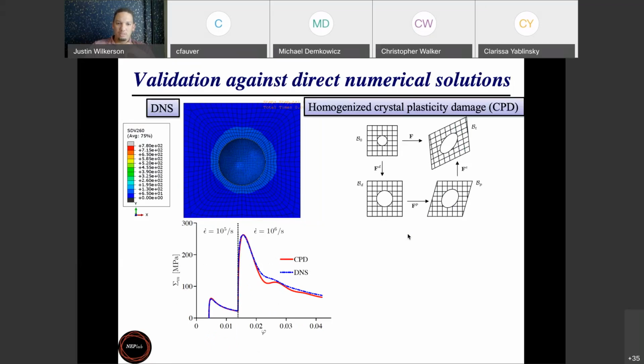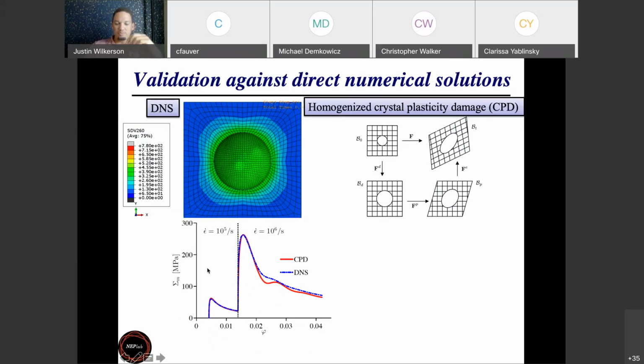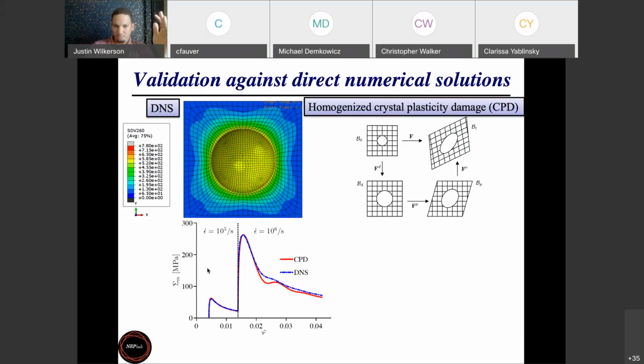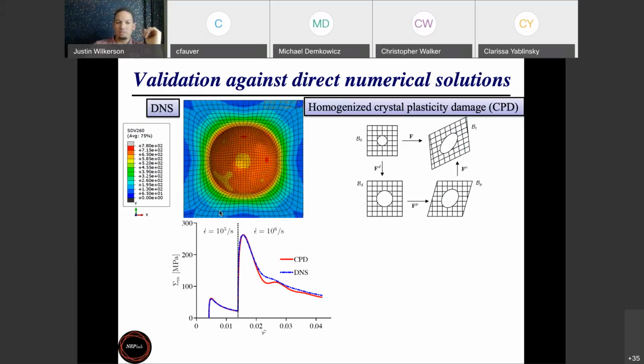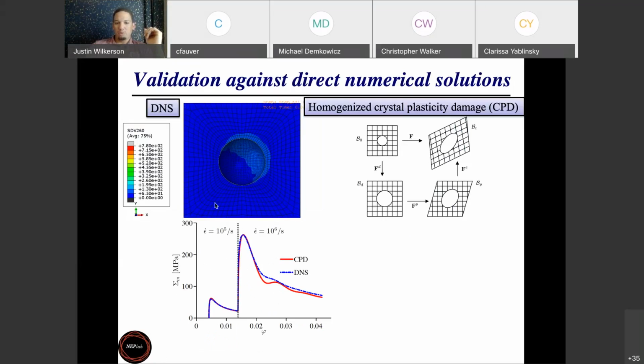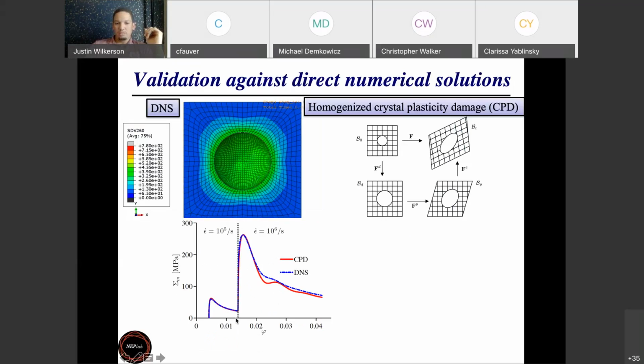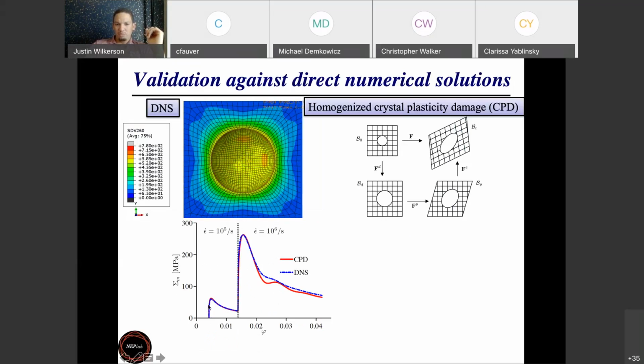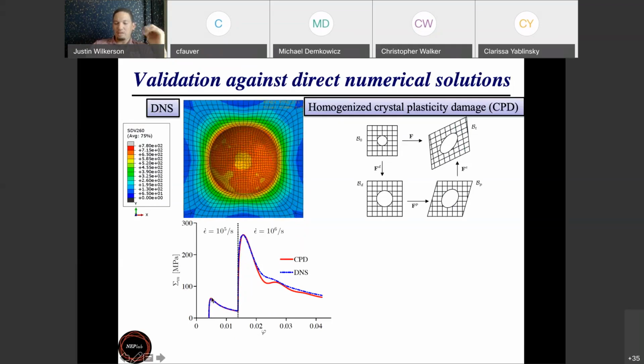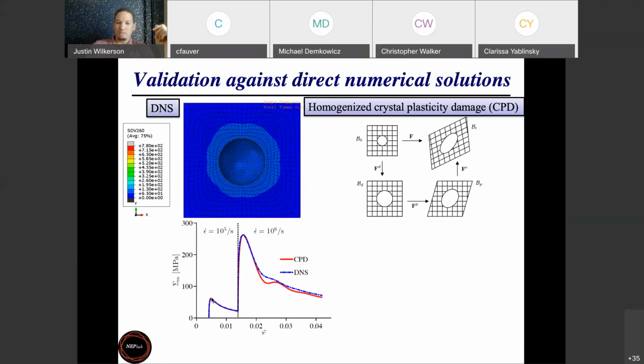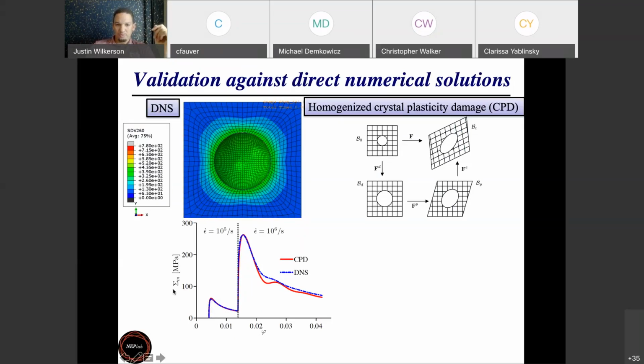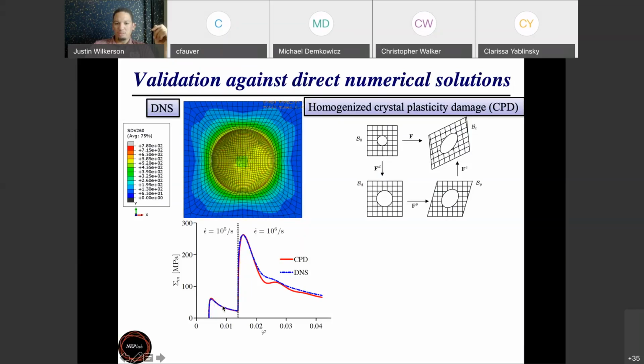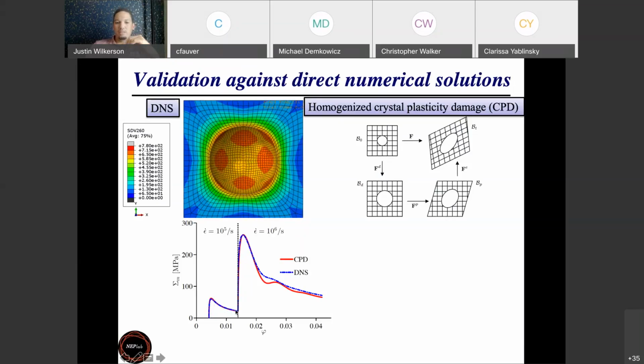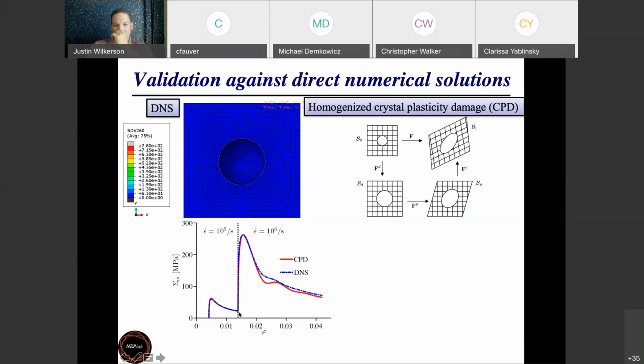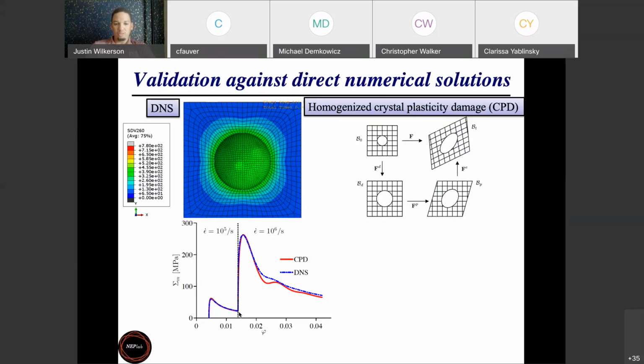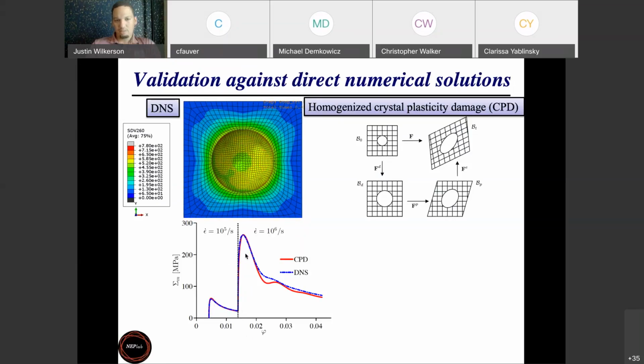So here in the bottom left is the evolution of the mean stress measured at the boundaries of the DNS calculation as a function of porosity, as the porosity is evolving. So what you see is you first elastically deform, then you start growing the void, and then you reach a peak. That peak stress would be like the spall strength under that particular loading situation. And then as I continue to grow the porosity, I get a relaxation of the stress. And then we do a fun thing out here at 1.5% porosity, where we actually change the strain rate dynamically.